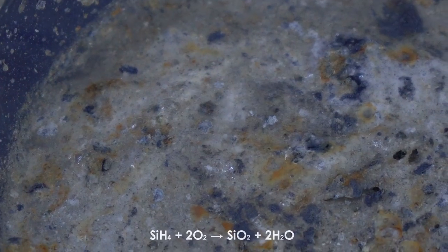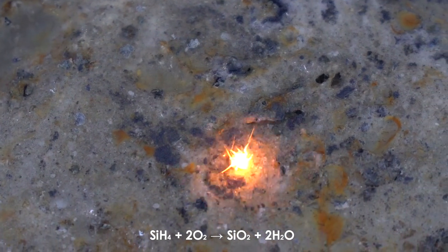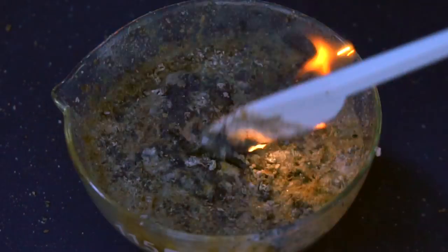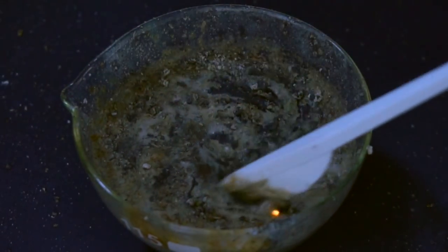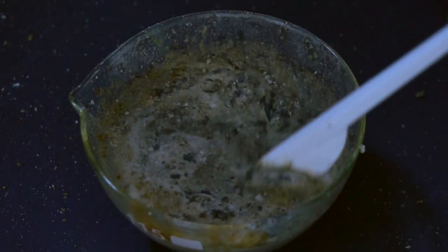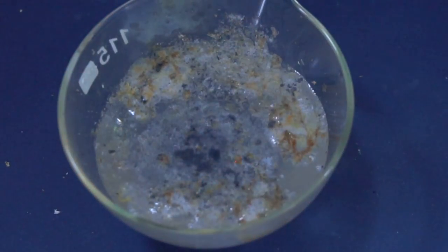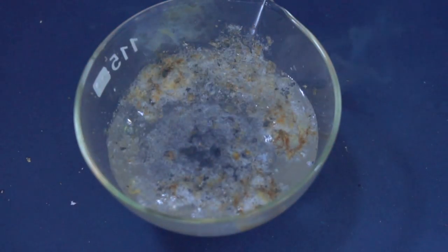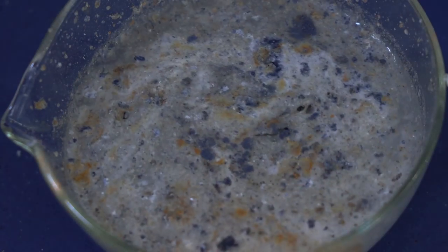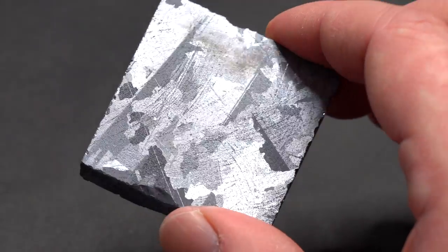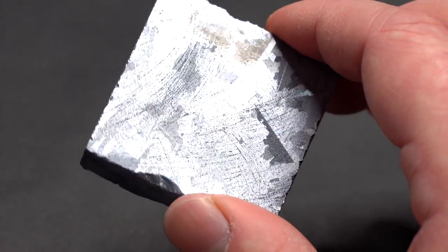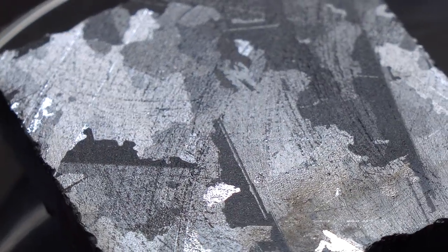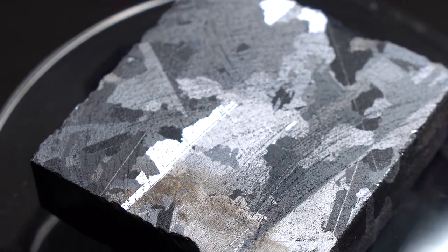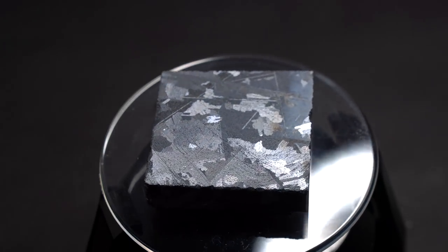When the silane bubbles react with oxygen, they immediately explode and burn down in air, producing water and silicon dioxide. It is worthy of note that the reaction between silane and oxygen is so spontaneous that it can be run at the temperature of liquid oxygen, that is at minus 180 degrees Celsius. If I ran this reaction in an inert atmosphere and could collect the obtained silane, I would use it for producing high purity silicon. When silane is heated to more than 500 degrees Celsius in an inert atmosphere, it breaks down into hydrogen and pure silicon, which is pure enough to be used in silicon semiconductor production. You can see such silicon on the screen. You can also see well that silicon has a polycrystalline structure, which means that it consists of lots of crystals, which are fused together.